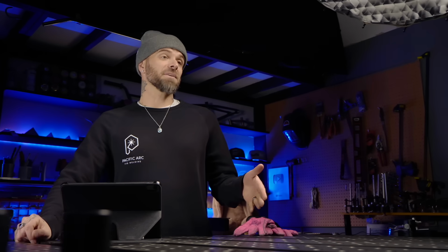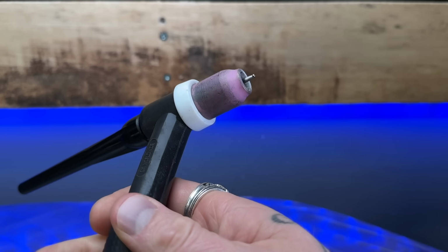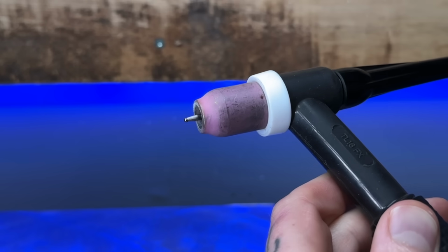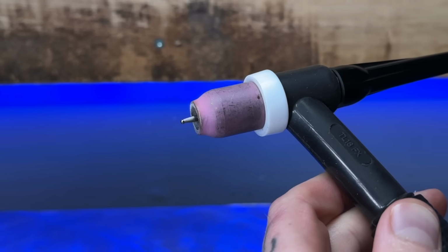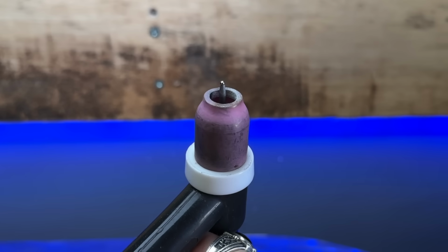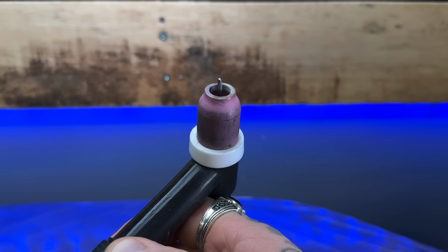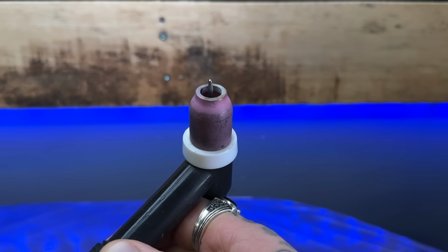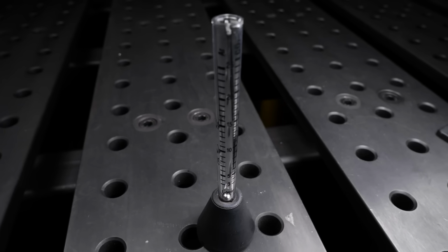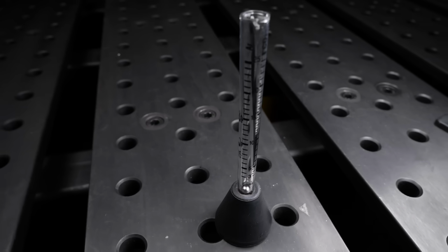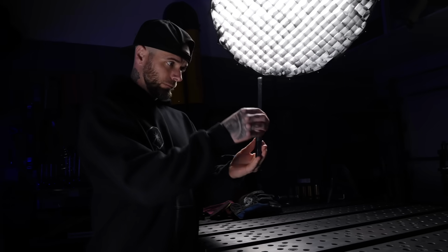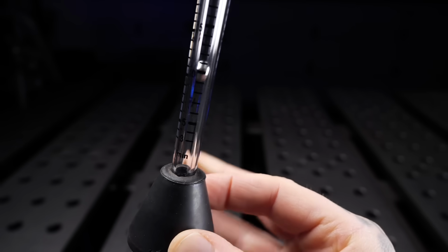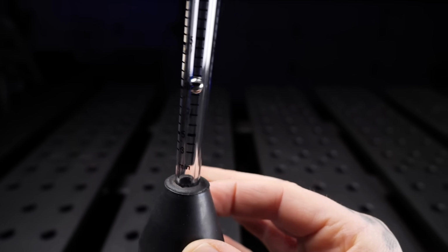Now, the volume of gas coming out of the torch changes in relation to the cup size that you are using. If you're using a smaller cup for aluminum, like a number 5 or something like that, we obviously, for a smaller cup opening, want to have less gas coming through it. Working with an aluminum setup like this here, I'm typically going to have about 12.5 CFH coming out of the actual torch head. And again, I'm going to double check this with this thing here. This is called a flow meter. We're going to put it on the end of the cup and we're actually going to measure the exact gas value coming out of the cup opening.